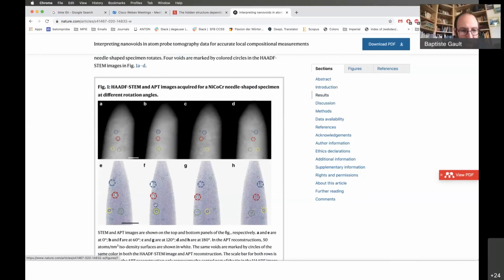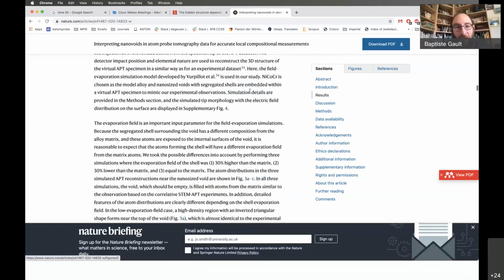And then in the atom probe, we actually saw this fluctuation of the point density. The point density was either doing this or sometimes doing more of a W shape. So sometimes it just drops and then increases and then drops again. This all depends on two things: the size of the void, but also whether there is a layer of different composition on the rim of the void. And we determine this based on simulations of the ion trajectories when you have a hole inside of the needle. So we could find either this case or that case, but this one didn't happen.